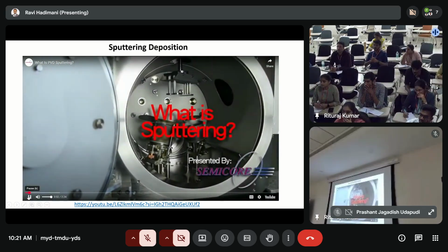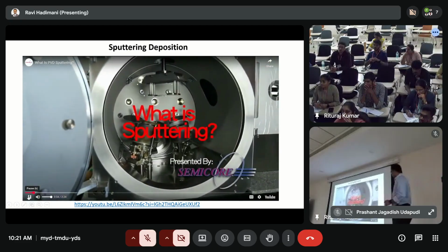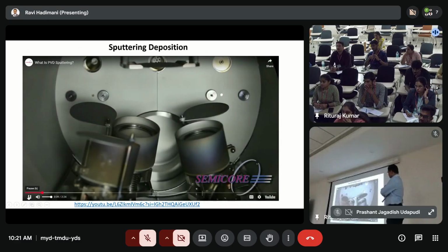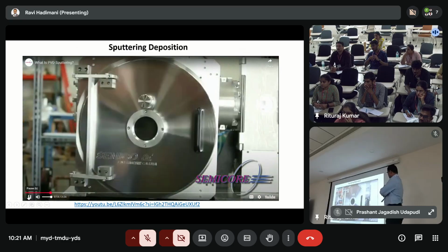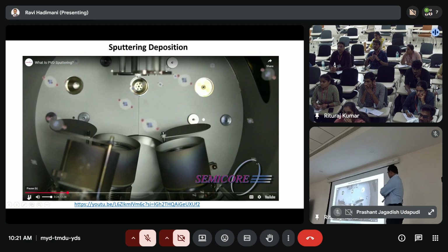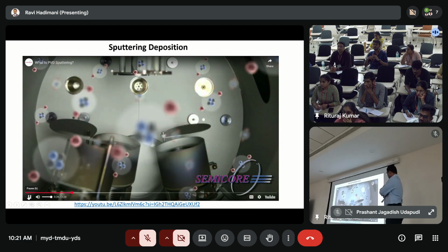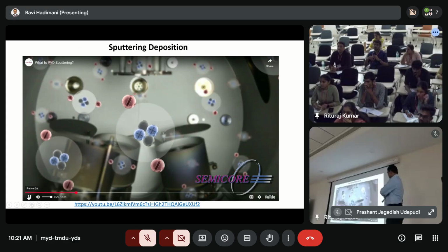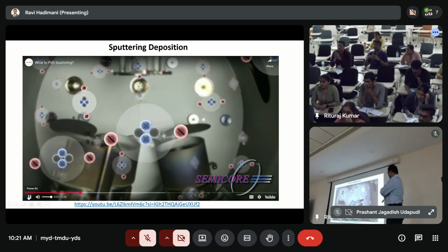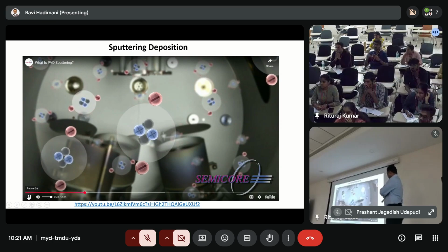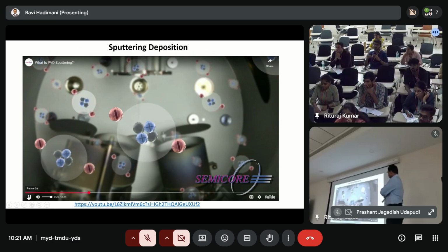So exactly how does the sputtering process work? First, your coating materials are placed on a magnetron in a solid form called a target. For highly pure coatings, you need a clean environment with only materials of your choosing. This is why the chamber is evacuated, to remove almost every molecule from the chamber. Then the chamber is backfilled with a process gas. Process gas species are chosen based on the type of material to be deposited. Common process gases include argon, oxygen, and nitrogen.